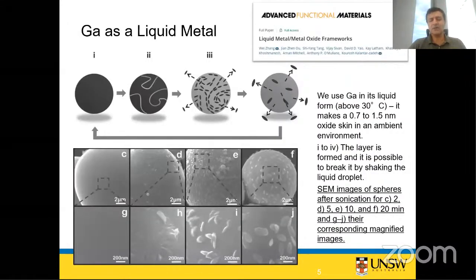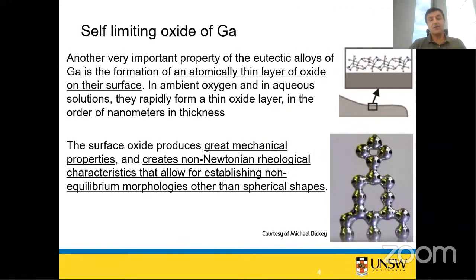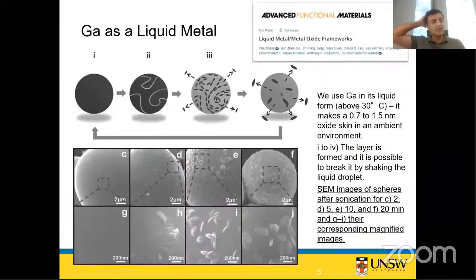It offers non-Newtonian rheological characteristics, this two-dimensional skin. Can we see the skin? Yes. Take one of the droplets of gallium and start shaking it, the skin breaks, the skin comes off the surface, and these layers that come off the surface can restack on top of each other. But the most important thing, as you see, is that when you start shaking it, you see the wrinkles, very similar to graphene and molybdenum disulfide, all two-dimensional materials. It wrinkles because it's very thin.